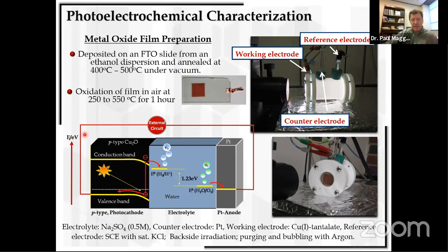And this is basically how our system functions. We have a Teflon container, a working electrode, and a reference electrode, which is SCE, and then we irradiate the film. This is different. This is not a suspended particle in solution. This is now a film, so that we only have to drive one half reaction on the surface.